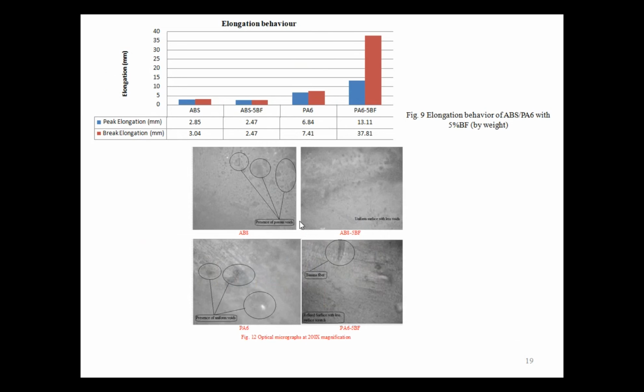But if I use this ABS or PA6 reinforced banana fiber, you see the percentage elongation, specifically the break elongation, is very high. So just imagine, suppose there is a chance of some movement in the earth, and there is a collapse of the whole roof, right? Because of the high elongation of this material, this will help me in better elongation, and the roof is not going to collapse immediately. The strength in the form of peak strength, break strength, modulus of toughness, Young's modulus, and the elongation for this material is better than that of the MS wires that we are commercially using for tying the iron bars in a construction site.